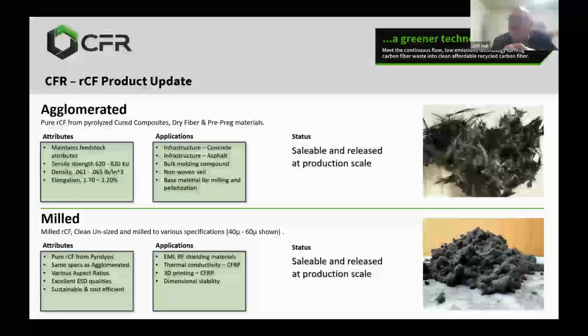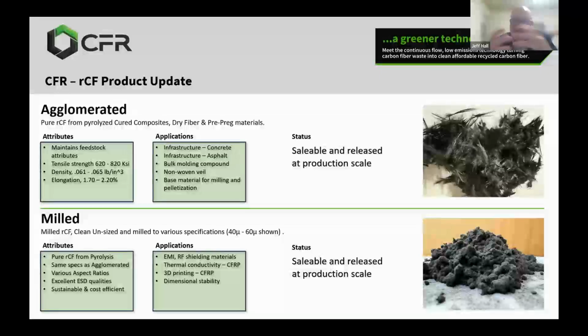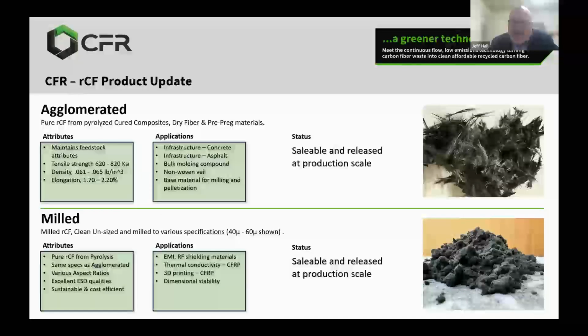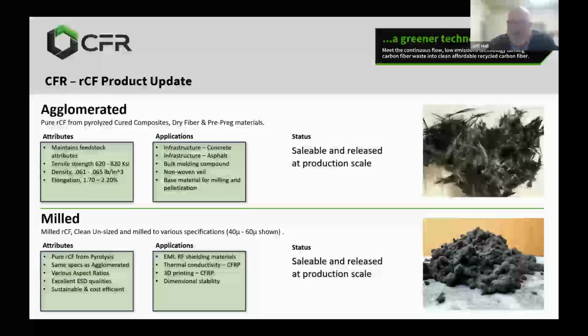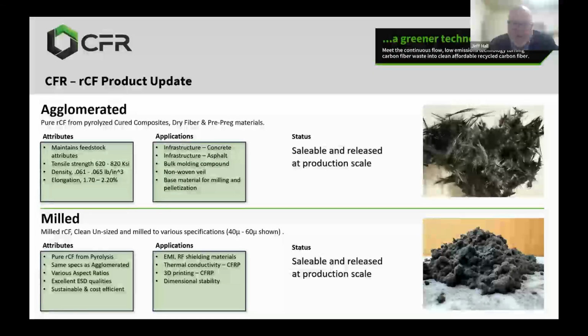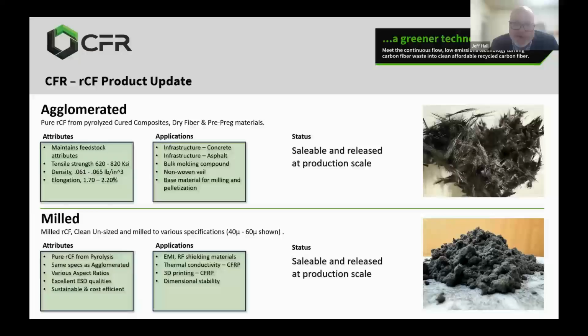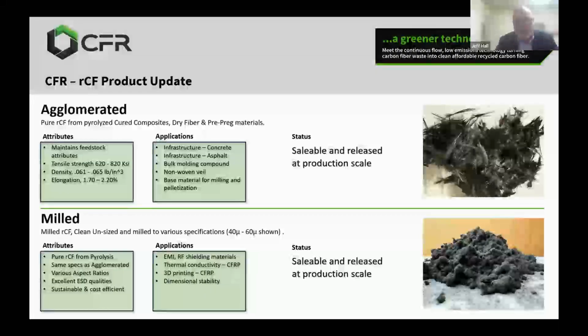So our agglomerated material can be used as is for applications like, for example, infrastructure applications like fiber reinforcement for concrete and asphalt. And we also use this material as the base product that we create other materials out of. For example, if you look at the bottom of the page here, you're going to see our milled RCF. So this milled RCF has all the same attributes as the agglomerated RCF, but it can be milled to various aspect ratios.